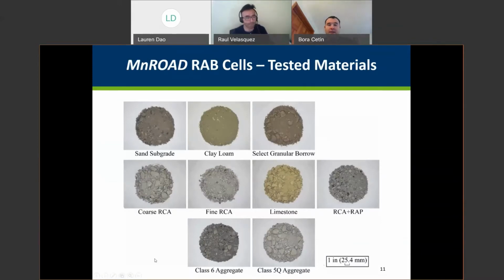Bora. Thank you, Raul. So thank you again, everybody, for being here. So these are the 9 different materials that we tested for the recycled base test sections at MnROAD that Raul just mentioned. Again, we had a sand subgrade underneath coarse RCA and fine RCA test sections, and clay loam subgrade under the RCA RAP mixture base and the limestone base. And we have a select Granular Borrow material here on the top, right above the sand subgrade and clay subgrades. And here are some pictures of the coarse RCA, fine RCA, RCA RAP mixtures and limestone.